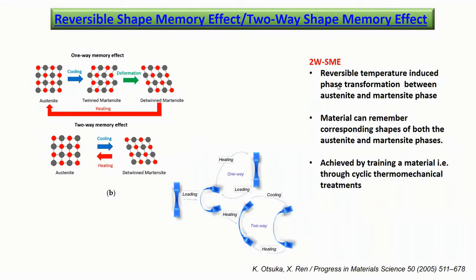So what happens here is that it can remember its shape in two forms. Not only can it remember the initial shape that has been given to it in austenite, but it can also remember the shape that has been given to it in the martensite. And to achieve this two-way shape memory effect, what is necessary is to train the material. Okay, this kind of terminology is very similar to our life, right? We need to train something to remember, right? The material also behaves, it's a smart material, that's how it is. So we can train it in two different phases, in the austenite phase as well as in the martensite phase, so that the material can remember its shape in the austenite and martensite, both ways.